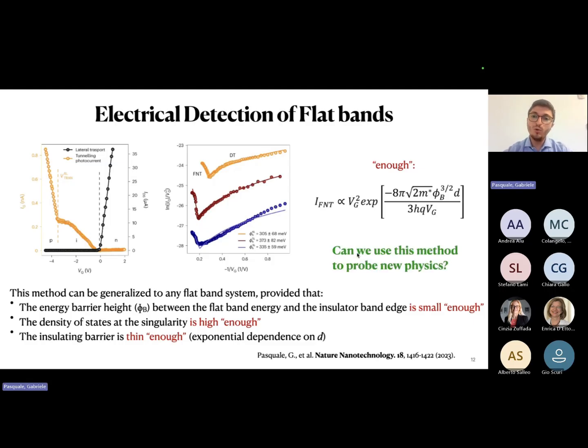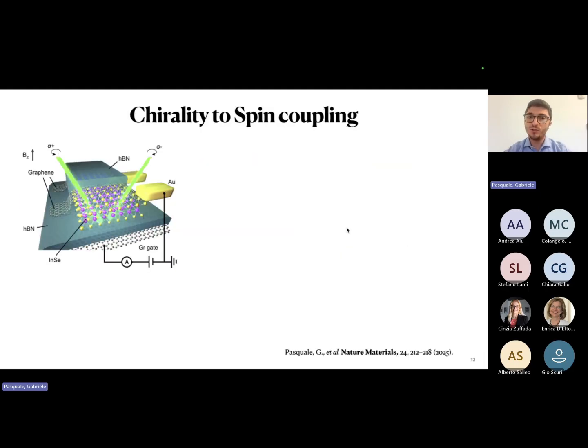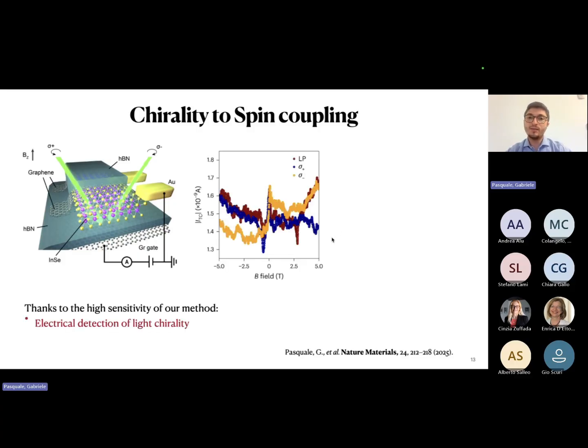So now the question is, can we use this method to really probe new physics in this system? And to this point, the answer is yes. We studied chirality to spin coupling in this two-dimensional semiconductor, and we performed the first electrical detection of light chirality in an originally non-chiral system. We split this degeneracy using a magnetic field, where at 5 Tesla, for example, you can see that for the blue and yellow currents there is a strong difference in current just by changing the light chirality.